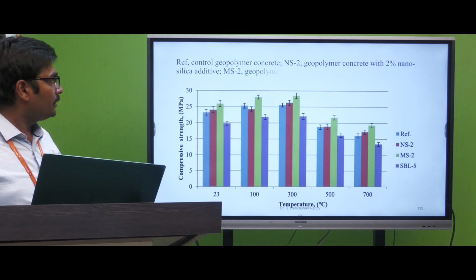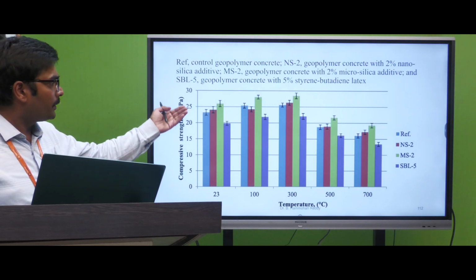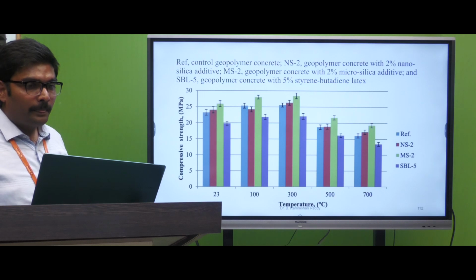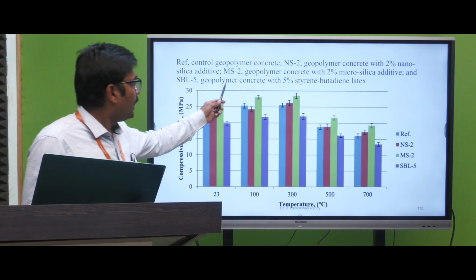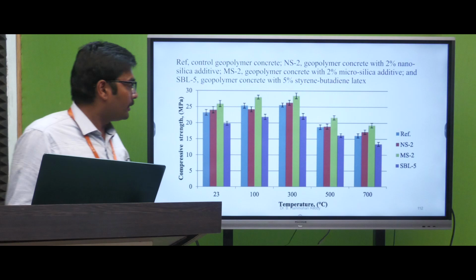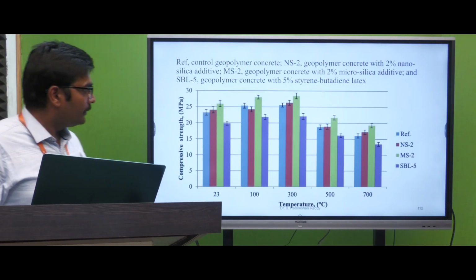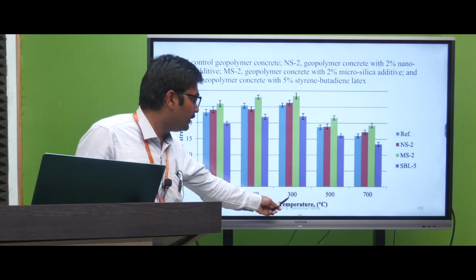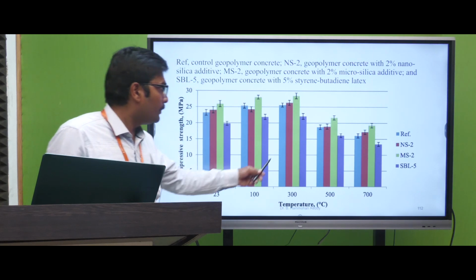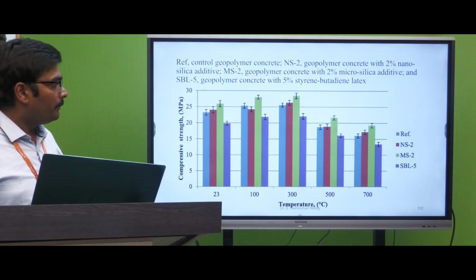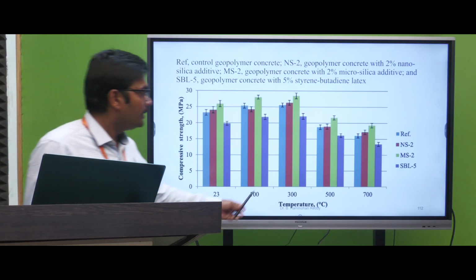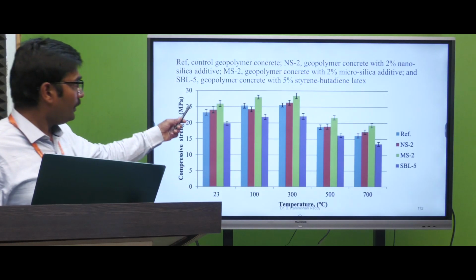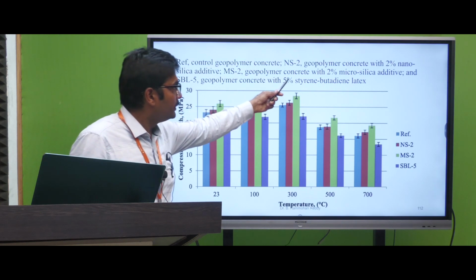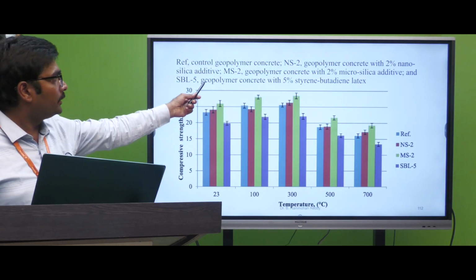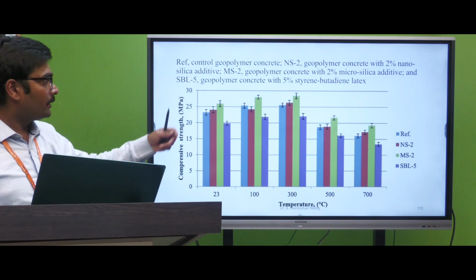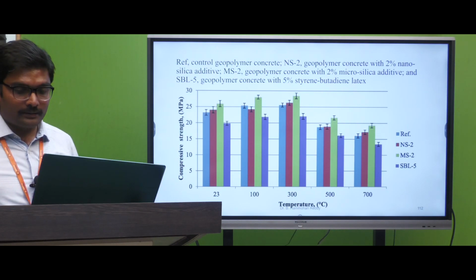And the compressive strength of the geopolymer concrete with the different proportions, which we can see here, like 2% nano silica additive or 2% micro silica additive. At different temperatures, the majority you can see at 300 degrees centigrade, the geopolymer concrete produced better compressive strength values. Particularly geopolymer concrete with 2% micro silica additive produced better results.